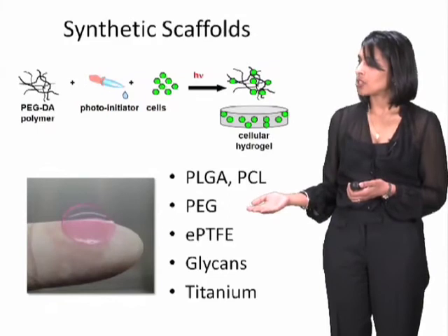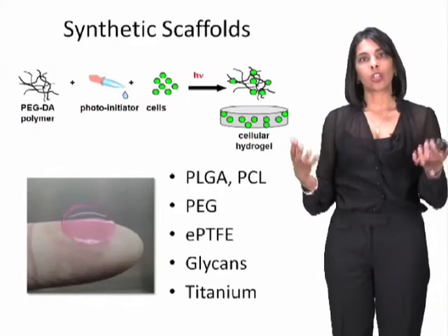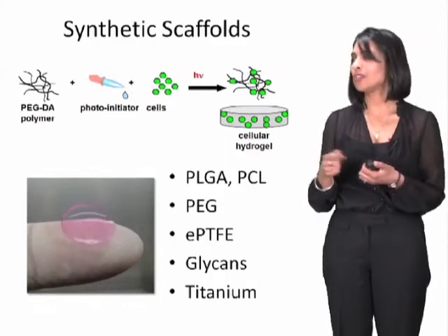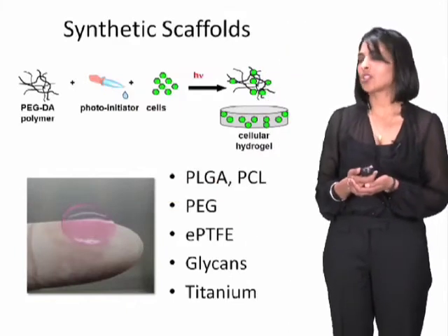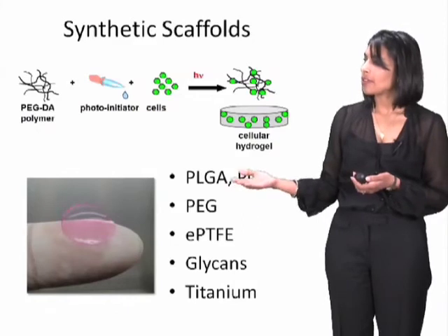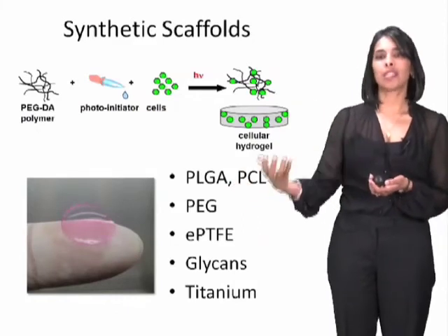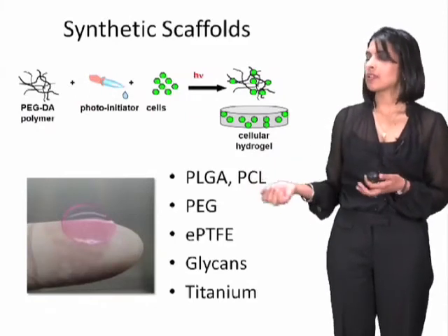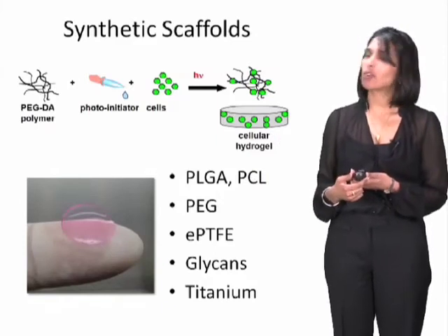So there are many, many novel polymeric materials that have been developed. Another very popular one, which has the property of being a hydrogel. Again, a hydrogel is a material that absorbs a great amount of water and has this sort of intuitive feel of gelatin. Here we have a polyethylene glycol, which is a very popular biomaterial these days. And you can see that it looks a lot like a soft contact lens. What's interesting about some of these hydrogel materials is that rather than being pieces of plastic, where cells can be attached to the plastic and they can remodel the plastic, these are materials where cells are embedded within the plastic. And this material in particular is very interesting because it can be cross-linked with light.